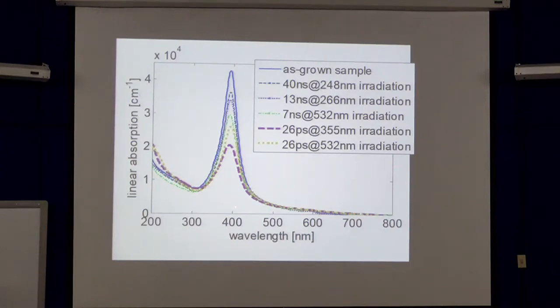For instance, this is the peak related to the absorption band of the surface plasmon resonance, that is a collective response of the electrons related to the material, for silver. But for gold, we have this peak in the green. For copper, we have it in this region. For platinum, for instance, we have it in the ultraviolet. For nickel, we have it in the blue.